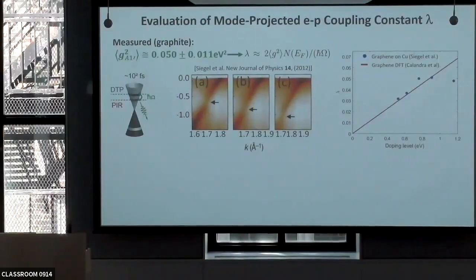Finally, this comes to a comparison with the data that we had shown initially. Unfortunately, it's really hard to do comparisons for the case of graphite, also because we are actually not working with graphite up here. We're down here where the chemical potential really is. We are working up here, so we wanted to do something that could be meaningful at this kind of density of states and extract a lambda.